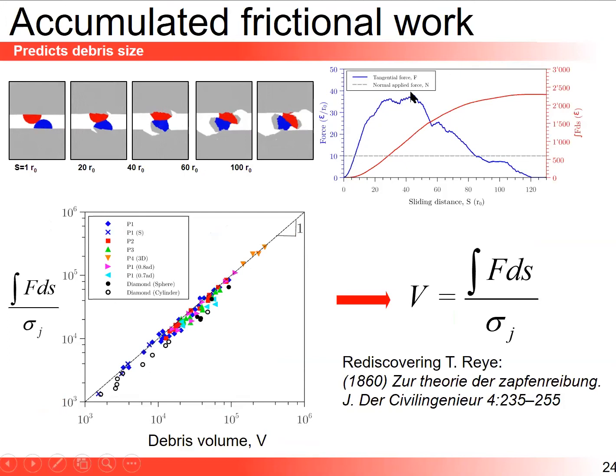You reach a maximum, eventually you decrease, you reach zero here. And if we integrate the blue curve, I'm getting this red curve. So that's the integral of the tangential force along the sliding path. This quantity, normalized by the junction strength, which is a material property that we control in our system, has, for units, length to the cube.